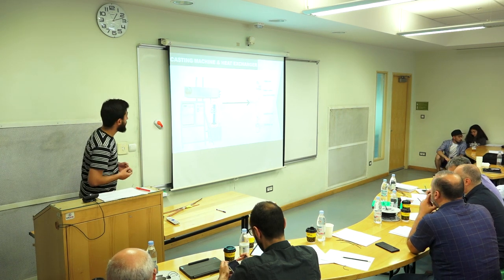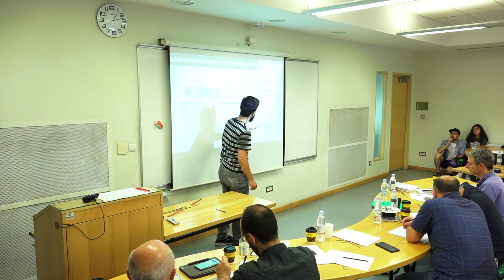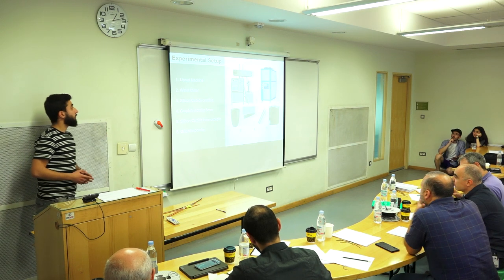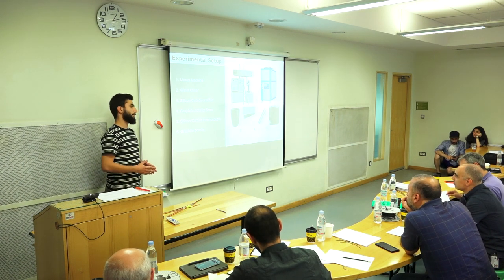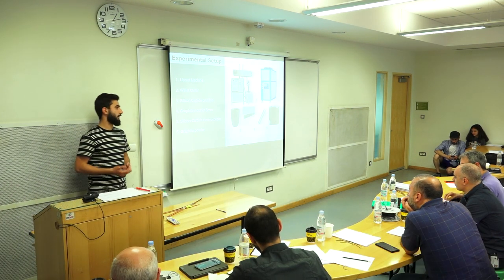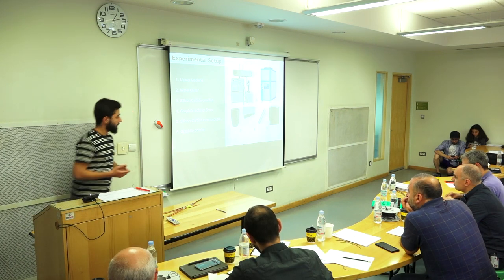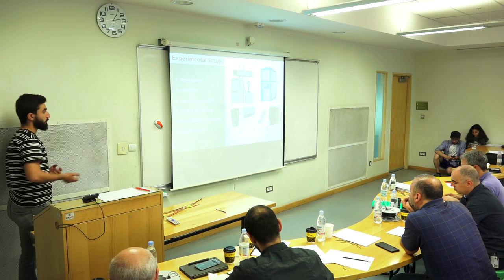Here you can see the machinery used for the experimental part of this research. This is the testing machine, and you can see the heat exchanger assembly, which features a steel heat exchanger, a graphite mold, and an insulating cup. We also used a water chiller unit for cooling down the machine, because the machine features an electromagnetic induction heating system that requires cooling. The heat exchanger also removes heat from the copper melt via cooled water.